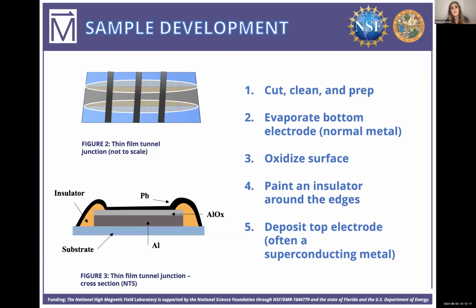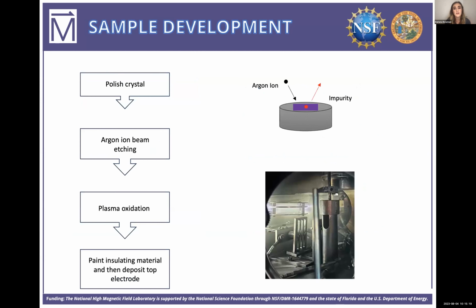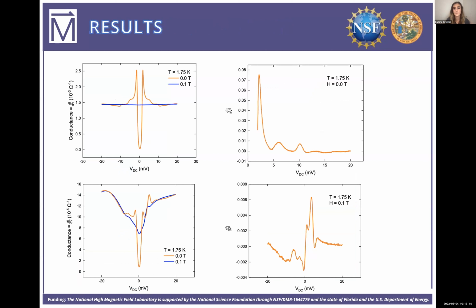In order to expand this to the new material, samarium hexaboride, we first start by polishing the crystal and cleaning it really well, then put it in a vacuum chamber and lower it to really low pressure. We use argon ion beam etching to remove impurities from the surface. And then we use plasma to oxidize the surface and create that insulating barrier. And then I took it out and would paint the insulating material on the edges again, and then put it in a vacuum chamber and deposit the top electrode, lead.